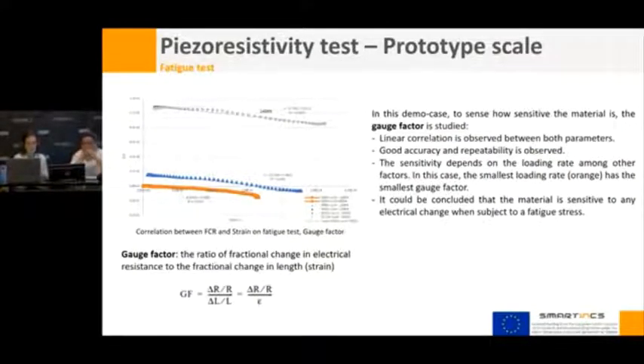To see how sensitive the material is, we use the gauge factor. The gauge factor is the ratio of the fractional change in resistance to the strain. As you can see here, these are just six cycles. A linear correlation is observed between both parameters, so good accuracy and repeatability are observed. The sensitivity depends on the loading rate; in this case the smallest loading rate, the orange line, has the smallest gauge factor. It can also be concluded that the material is sensitive to any electrical change when it is subject to a fatigue test or stress.